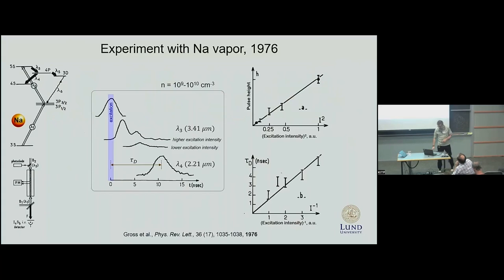Subsequently, the superfluorescence experiment was repeated on sodium vapor by a group led by Serge Haroche in France. Again, they used an elongated sample cell with dilute vapor, much lower number density. Again they observed delayed emission and its dependence on excitation intensity, and again the pulse height, the peak intensity, was proportional to the excitation intensity squared, as expected.